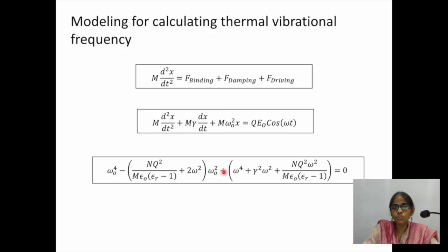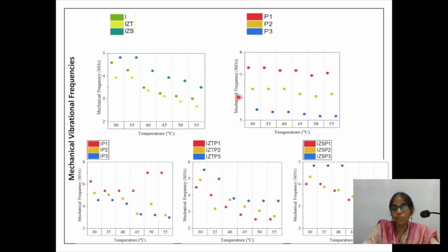From here, we wanted to understand the molecular dynamics. We did a small theoretical modeling, where we assumed that every protein-nanoparticle complex is acted upon by three forces: binding force, damping force, and driving force. We solved the differential equation, and from that we got a quadratic equation for the mechanical vibrational frequencies. Theoretical values of mechanical vibrational frequency at different dielectric constant values were extracted, which is plotted here.